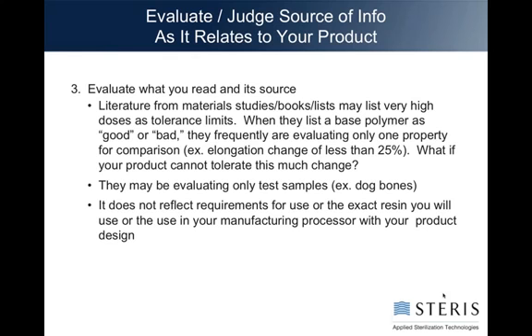They also are frequently evaluating test samples or dog bones or tensile bars. They're not evaluating a product with bends and curves and stresses on both sides of a bend. All of those things impact the effect of oxygen permeability, cross-linkage potential, and the added stress drives more oxidation. So you have to always know that the tables are great as a starting point. They are not a replacement for testing. They do not reflect the exact resin you will use either. They are generalized tables unless you're getting them from the resin supplier.